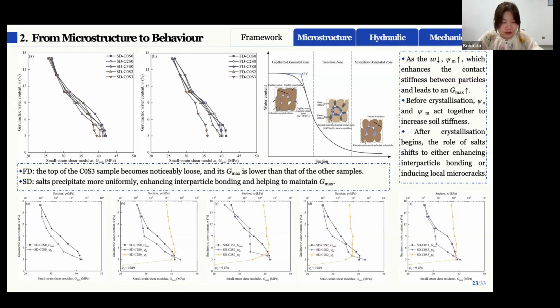And after crystallization begins, the role of salt changes. It can either strengthen interparticle bonding through precipitation, or in some cases, induce local microcracks, which may weaken the structure. And the drying mode also plays a role, because under slow drying, salt precipitation is more uniform, which helps maintain interparticle bonding and preserve Gmax. In contrast, under faster drying, especially for the S3 sample, the top part becomes noticeably looser, leading to a lower Gmax compared to the other samples.